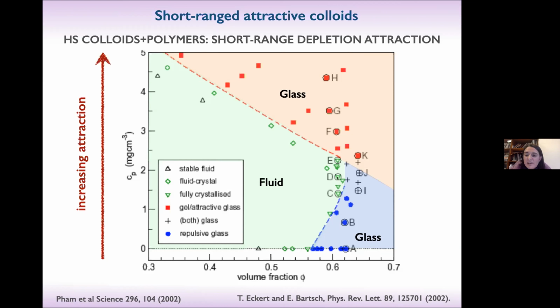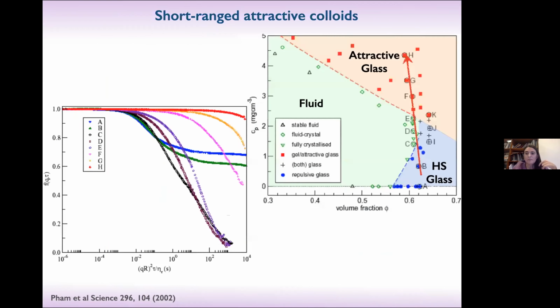And the very interesting thing is that here, there are these green triangles that are systems that actually were able to crystallize. Basically, it's very interesting because here you go from something that is glassy, at very large packing fraction, we talked about the cage effect, the hard spheres are very, very dense, you add the polymer, so you make it even more dense, but for some reason they speed up, you will see in a minute, and they are able to go to underlying equilibrium, partially crystallize, but then you further add polymers and they glassify again.